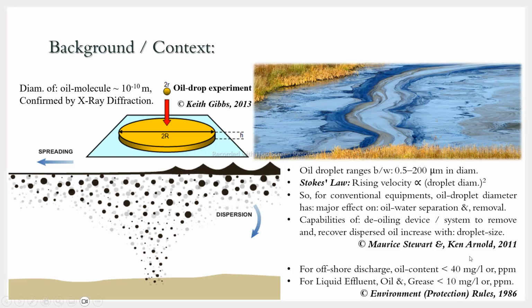There are environmental rules and regulations. As per the 1986 Environmental Protection Rules, for offshore discharge the oil content must be less than 40 ppm in the water, and for onshore discharge, like the liquid effluent from industries, the oil and grease content must be less than 10 ppm without dilution. So we can see that the oil molecule is in the angstrom range, and the oil droplet ranges between 1 to 100 micrometers, let's say, in diameter.